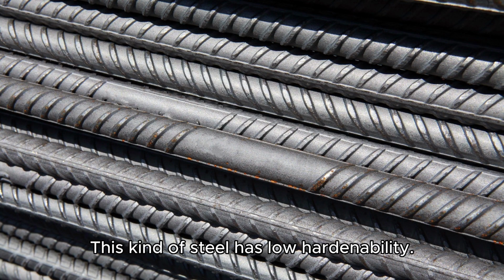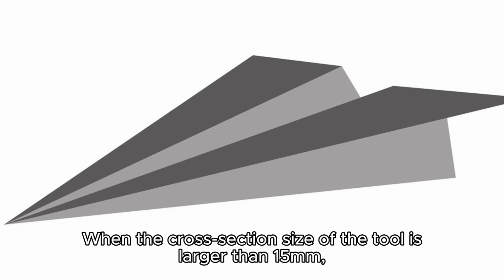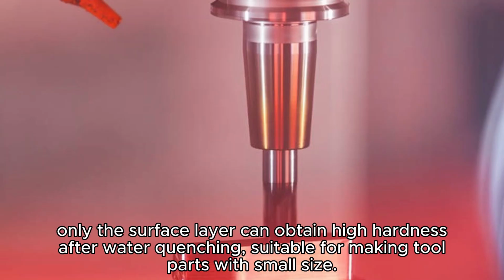This kind of steel has low hardenability when the cross-section size of the tool is larger than 15 millimeters. Only the surface layer can obtain high hardness after water quenching, so it is suitable for making tool parts with small size.